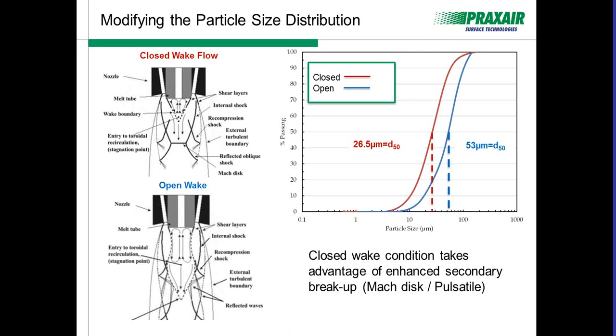So we could actually use these high-speed videos to confirm that this mechanism is truly occurring. The advantage here, like I said, is that you're already making fine powder in the close-coupled format. But if you move to closed wake, you can shift the average particle size by about a factor of 2. When you see a notation called D50, that represents, by volume, the particle size below which half of the particles fall. So this is going to be your average particle size for an atomization heat.